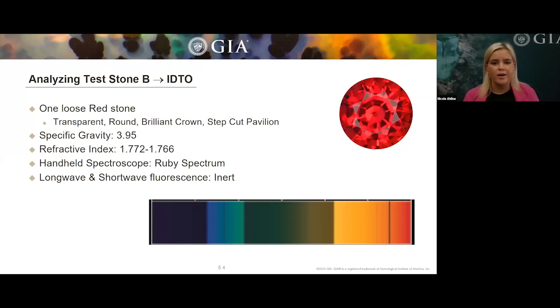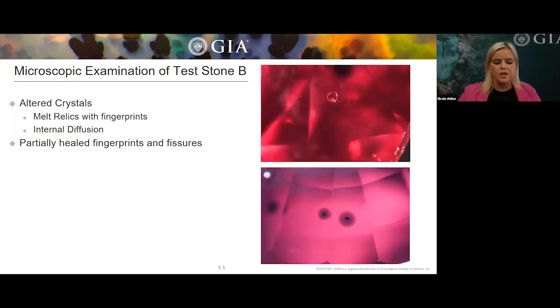We're going to check that long wave and short wave fluorescence. It is inert, which means that this ruby would not qualify for that pigeon blood color because we need that low iron, high red fluorescence. Internally, the gemologists are noting that there are altered crystals and melt relics. These are indications that this stone saw high heat treatment, so it was heated at a very high temperature. We also have internal diffusion that you can see down here in the bottom photo. They're noting partially healed fingerprints and fissures. So not only was this ruby heated, but it was heated at a very high temperature.